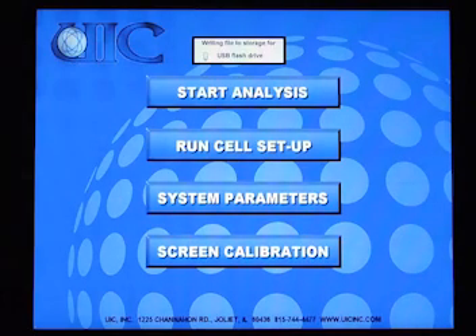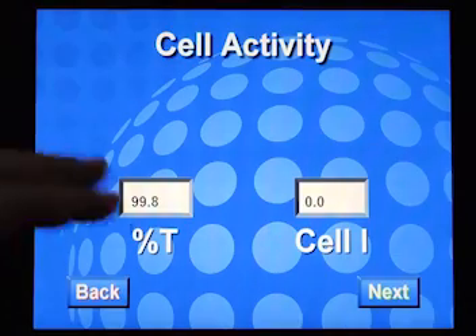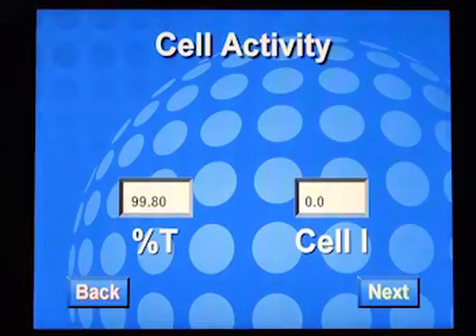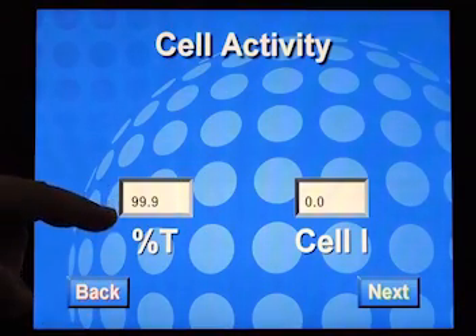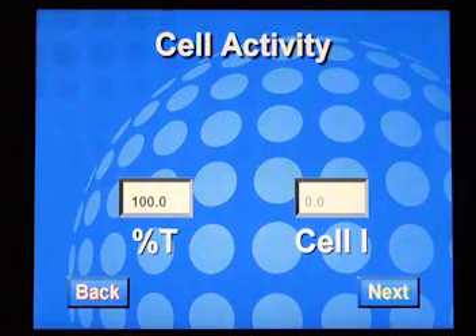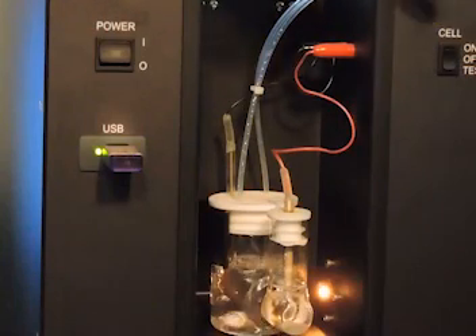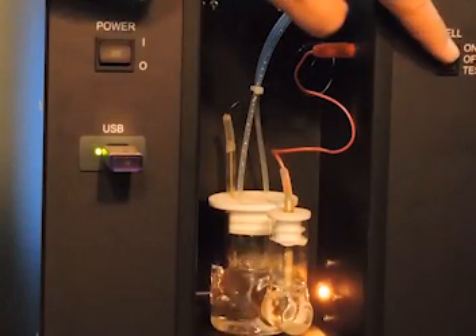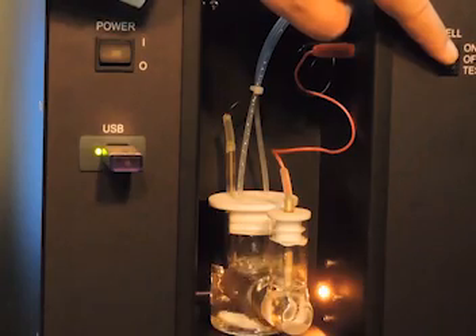Titrating the cell. Press Start Analysis. In this step, we'll titrate the cell down. The cell should be at 100% transparency, and the cell current should be 0. Flip the cell current switch to the on position. The cell current should change to 200 milliamps and the transparency should begin decreasing.